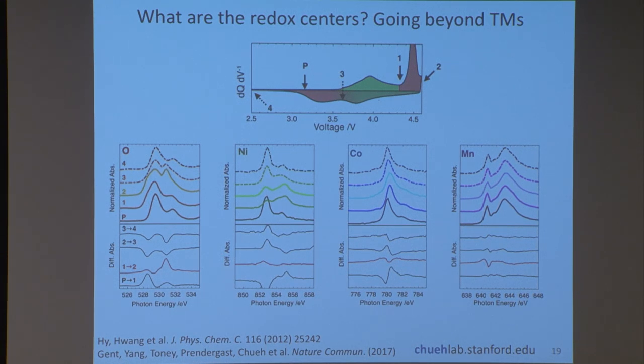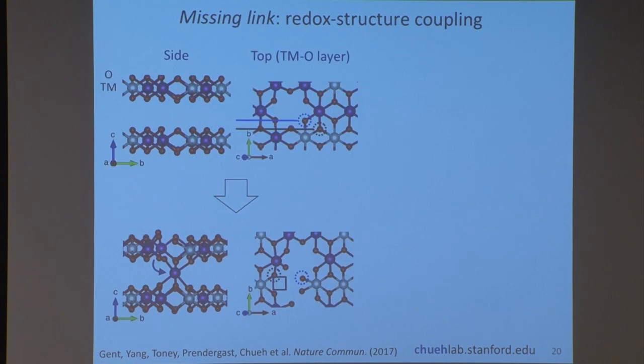So we wanted to understand how we're able to perform redox chemistry beyond the transition metal. The advantage is obvious. If you can do this, that means you can get the extra capacity. And that's what we're seeing here, that you have extra capacity 40% beyond what is possible with the traditional material simply by putting more lithium in. But what is not understood is why. And this is where the point defects come in.